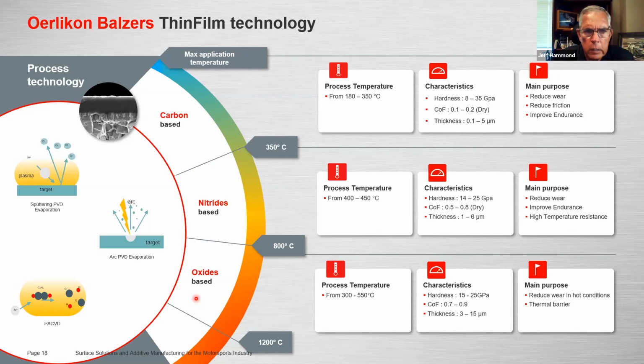With the coatings you have just recently showed us, is your diamond coating the hardest in your family, or is there something that's even more durable than that? No, today when we look at tribological applications, where we look at friction and wear, DLC remains the highest one. We are talking here up to 35, 40 gigapascal hard. So it's probably 4 to 10 times the material hardness, depending on the substrate. So here the DLC family is going to be really the highest hardness that we can get at the moment.